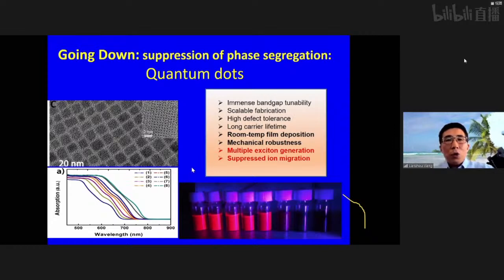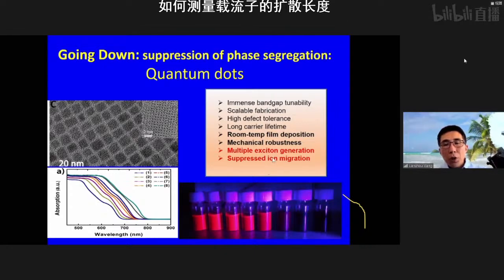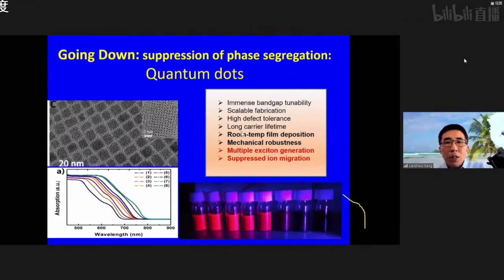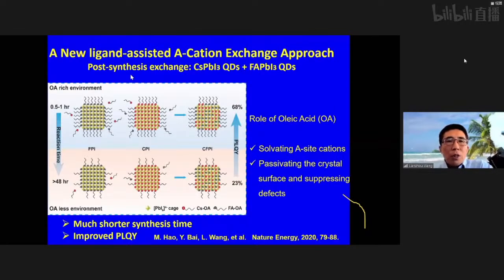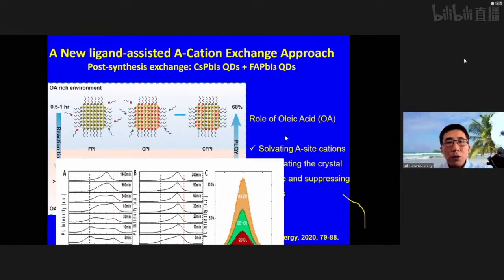But before that, we first need to develop such a type of perovskite. Recently, we developed a new class of perovskite quantum dots, which have quite a unique, good shape and also a tunable band gap by changing the composition. These quantum dots have a lot of unique features compared with the bulk counterpart, like multiple exciton generation, also very good stability, and suppressed ion migration. We use a new ligand-assisted cation exchange approach to produce mixed cation, like cesium and FA based, lead iodide quantum dots, very efficiently and in a very short period of time. I will not go through the details.